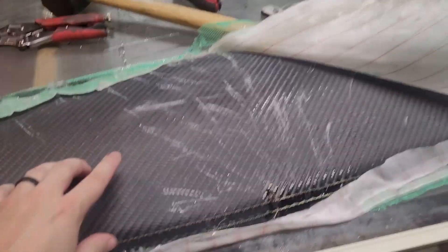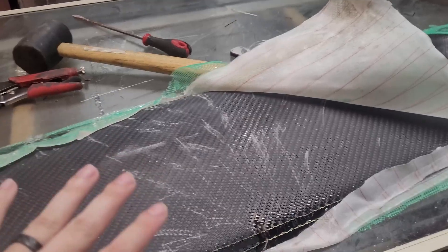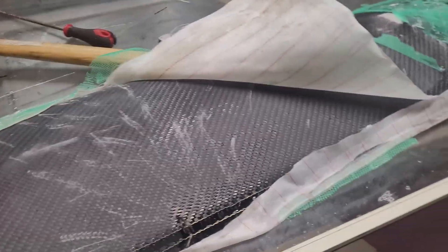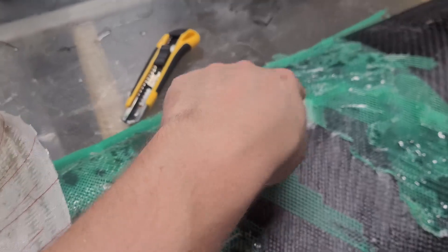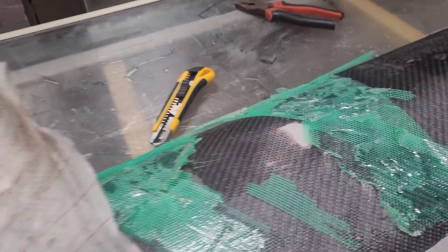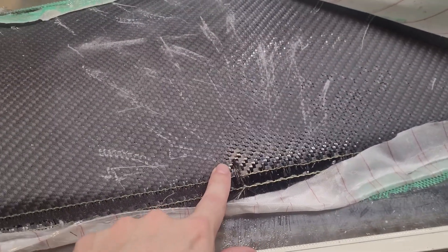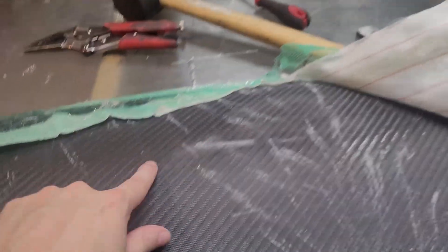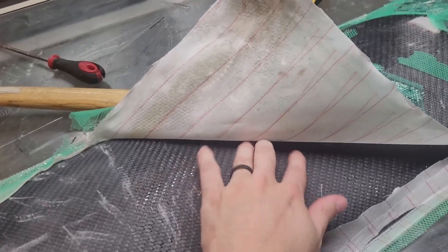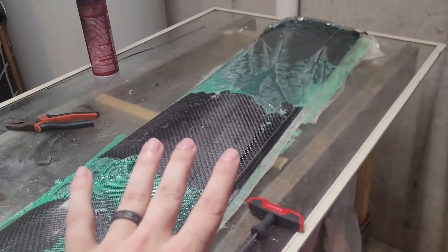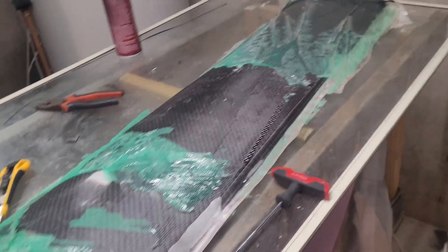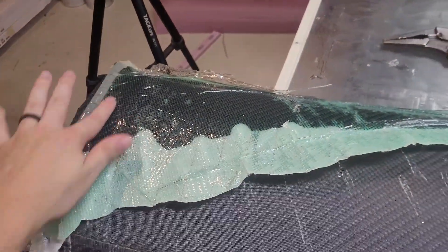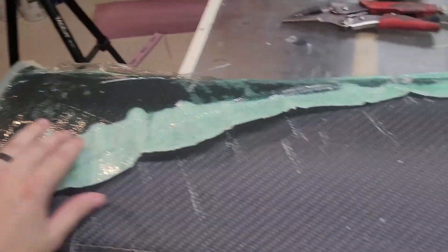Okay, so it's actually turned out way better than I was expecting with every problem that I had. It looks like there's a dry spot here that I could probably just refill with some resin when I get to it. And there's a dry spot here, but that's so close to the edge, it might get cut off. And all these marks are just from taking the screwdriver and getting it under the peel ply to pry it up, because with this much surface area, I can't just pull it up by hand. It's not working, especially because when the vacuum died, I got pools of resin in different places.